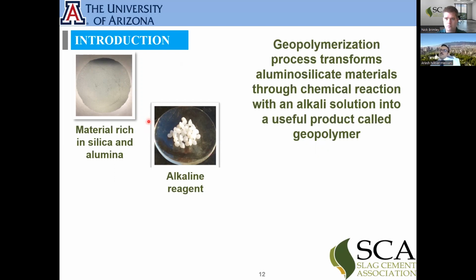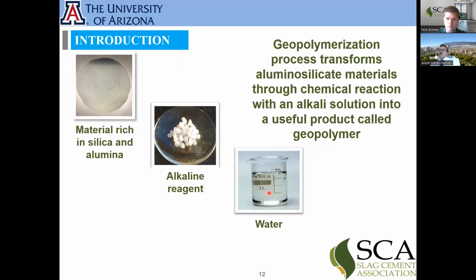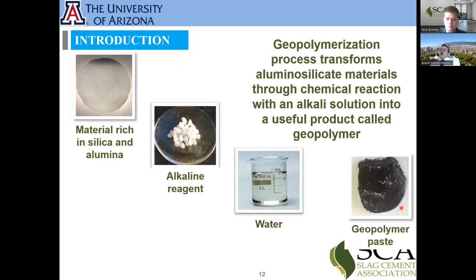These days there is some research being done using acidic activators. In terms of alkali activators, we could name sodium hydroxide and potassium hydroxide, and in terms of acidic activators, we could talk about phosphoric acid. And then we have the water, so we mix them and we produce this geopolymer paste. Then we have some curing happening on this paste, and then we will have the construction material, which we are going to talk about.